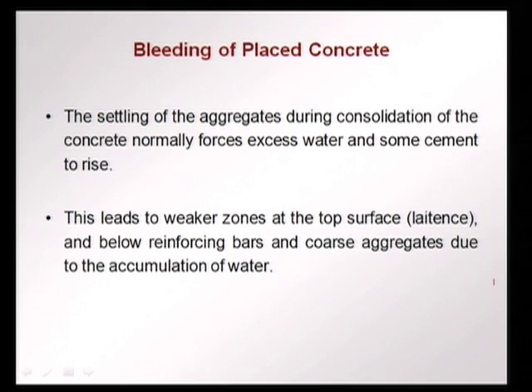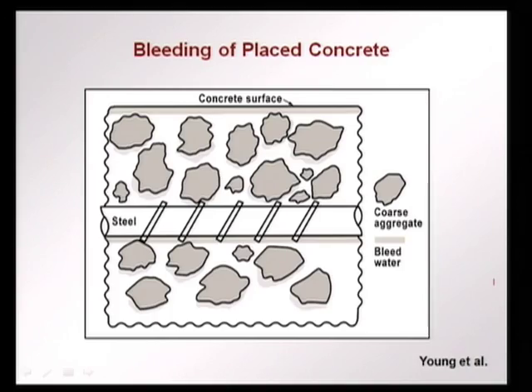hardened concrete. You will see a shiny surface at the top which is rich in paste or water, that is called laitance. There is accumulation of bleed water below reinforcing bars and coarse aggregates also. As the water moves upward, it meets obstacles in the form of coarse aggregates and reinforcement bars, and if the compaction time is not sufficient or the energy is not sufficient, this water stays below the reinforcement bars and the coarse aggregates, obviously leading to lower bonding and weaker interfaces.